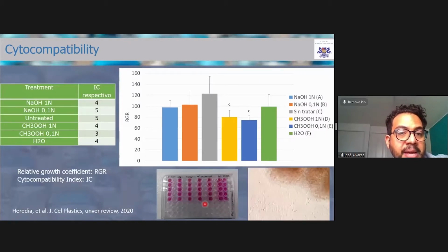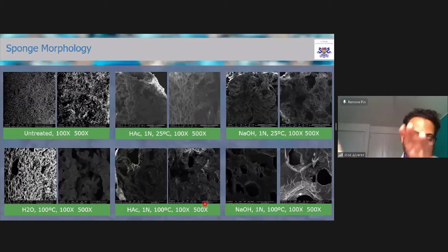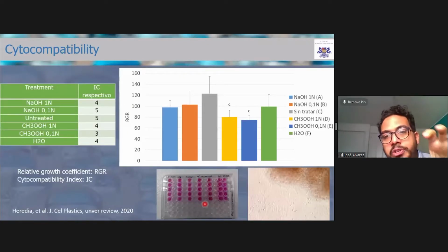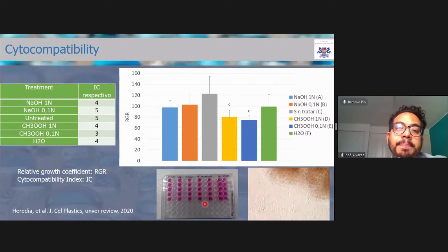And here you can see the untreated, which is very similar to the water treated sponges. Then of course, we did a lot of material characterization. I'm only showing you here some of the cell work. We demonstrated that the acid treated samples were not cytocompatible according to the norms that we used. So the alkaline treated ones were the most cytocompatible.